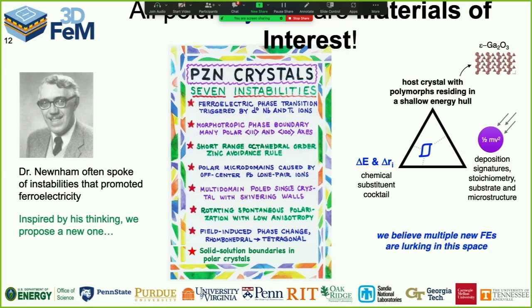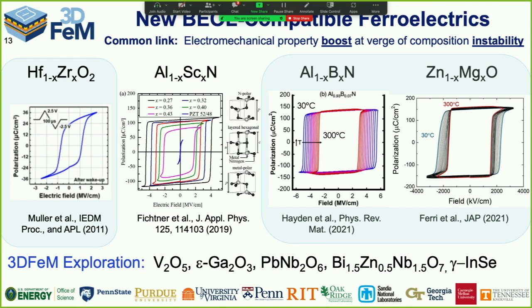always, when you poise the material at the brink of a structural instability, the susceptibilities go up. I should be able to shove atoms around easier when there's a propensity for moving them. And so we speculate that if you take a phase diagram, poise the material near where there's going to be a structural phase transformation, we might be more likely to generate ferroelectricity.